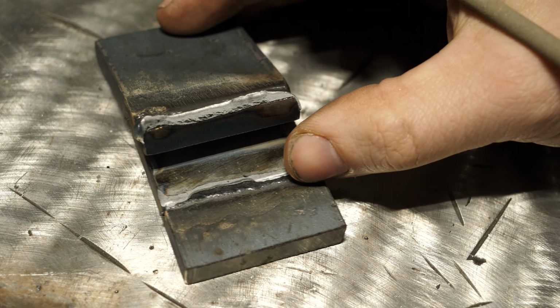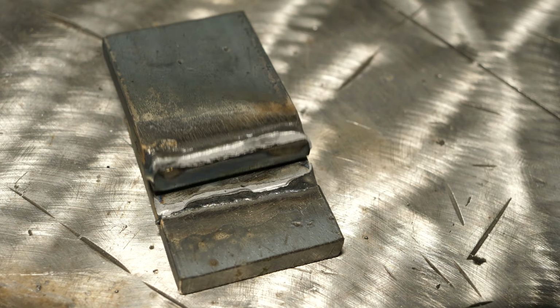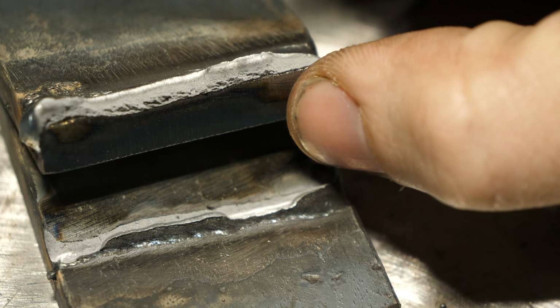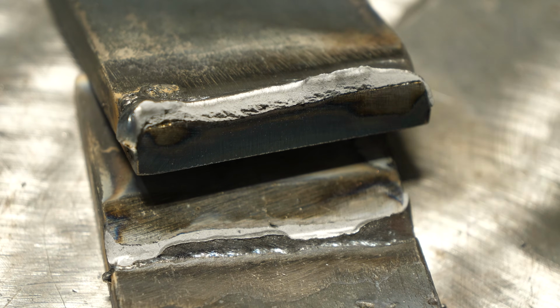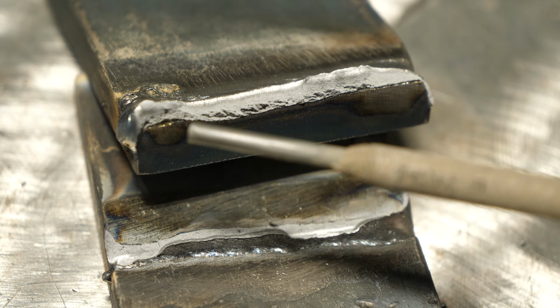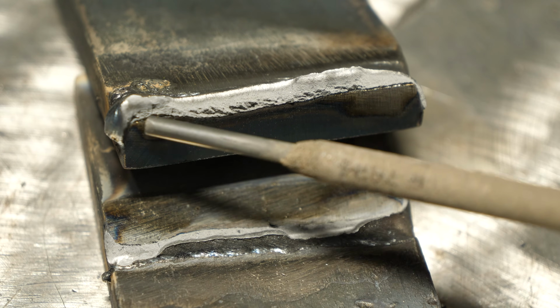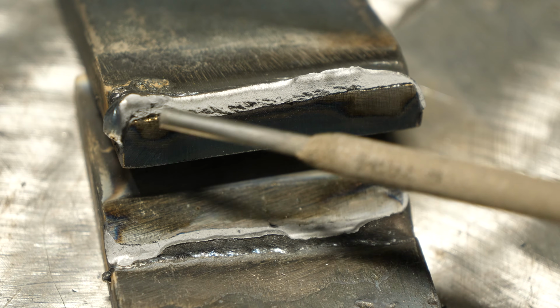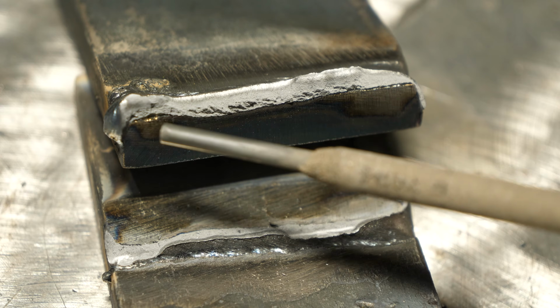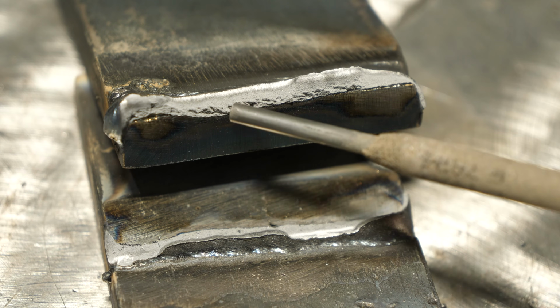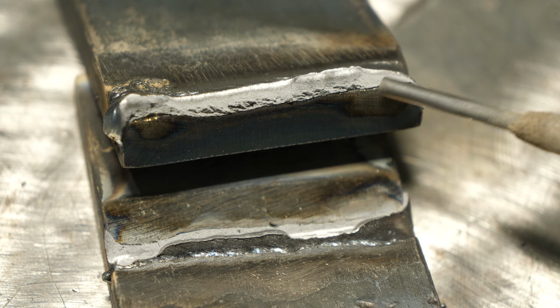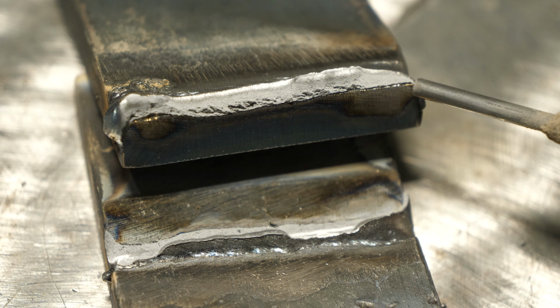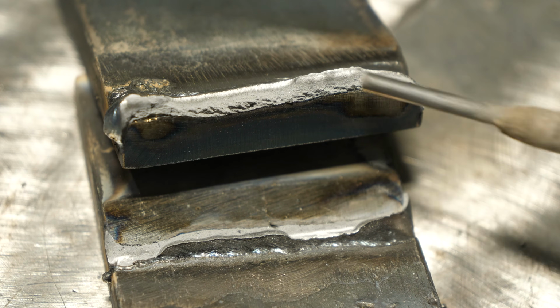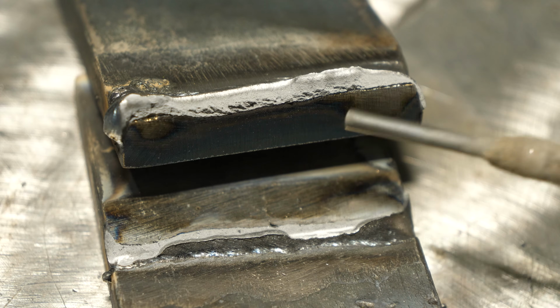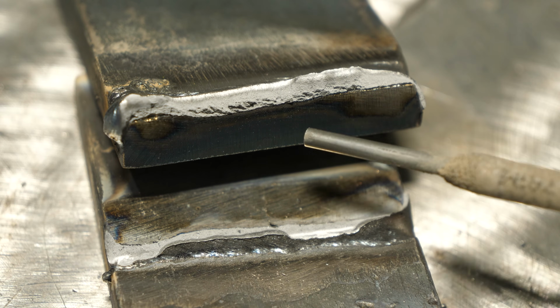So when we look at this guy, and let me zoom in for you, we have some penetration. The first part of the weld is pretty cold, as expected. I had a rough start, settled in, we had some penetration, and then near the end it tapered out with virtually no penetration. So this was the bend towards the face. This is, I would say, typical results.